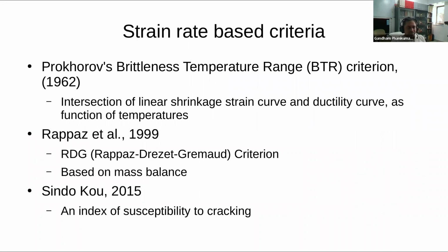Then there is a very celebrated criterion that everybody should hear about, the so-called RDG criterion, which explains why cracks form in any solidification process. It is explained so beautifully that it is applicable for casting, welding, and additive manufacturing, in all problems where solidification takes place. And Sindo Kou simplified that particular paper by taking a small portion of that analysis to give a gradation of alloys which will crack more and which will crack less. That kind of gradation, called the cracking susceptibility, was very useful because it lets you grade one alloy as more crack prone than another. However, it doesn't help you in identifying conditions under which crack-free solidification can take place. That's a limitation of that criterion.